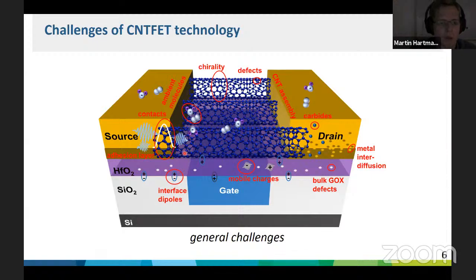And the next thing you need to keep in mind is the ambient molecules. Are there ambient molecules close to the CNTs at the contact sites or in the channel region? For example, water and oxygen are known to act as really strong P-type dopants on the CNTs. And when you passivate your device, so you remove the water and the oxygen from the device, then your current drops quite a bit and your threshold voltages shift, and you need to invest quite some effort again to get this P-type doping, to get the performance of passivated CNT FETs when you compare them to unpassivated devices. And this is quite interesting.